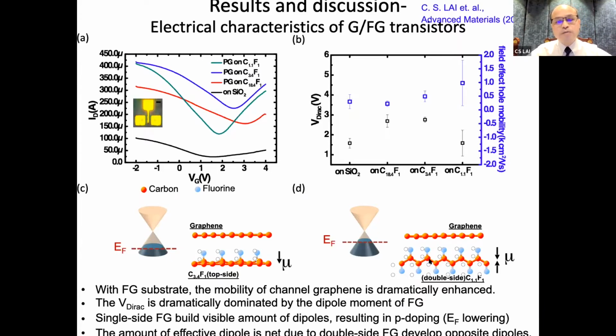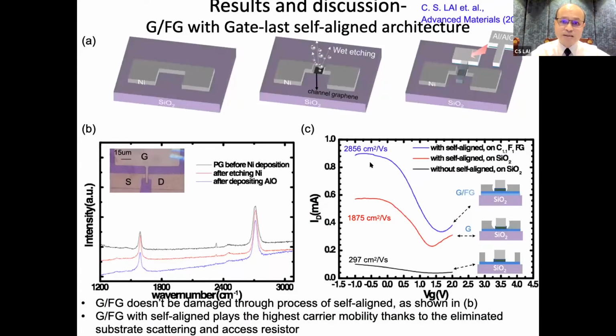If we use this spatial preparation of the dielectrics, the charge scattering can be fully prevented by dipole compensation. As you know, dipoles are a charge scattering source for the graphene carriers in graphene transport. So we prepare the 2D dielectric fluorographene on top of graphene or underneath graphene, like a sandwich capping layer. With graphene capped on top or underneath with fluorographene, we can have high performance graphene transistors. Here the mobility can reach almost 3,000 centimeters squared per volt second.